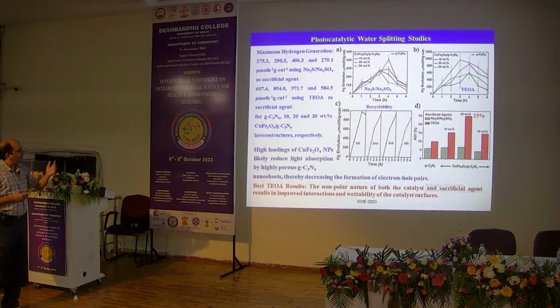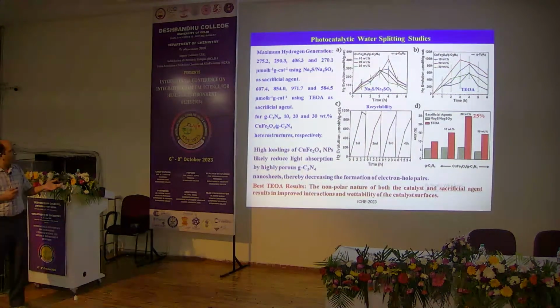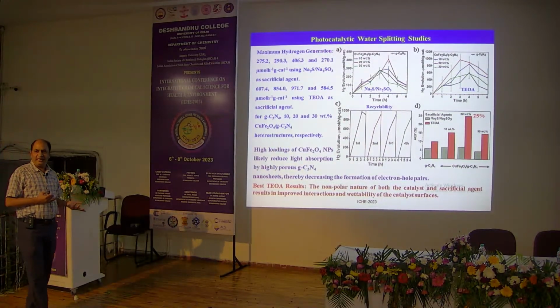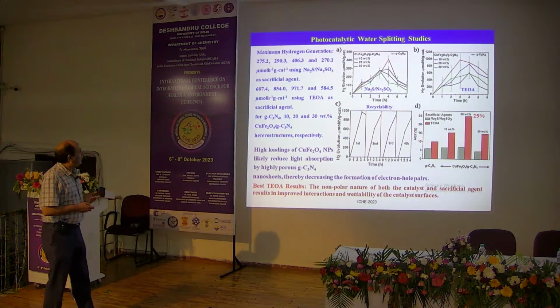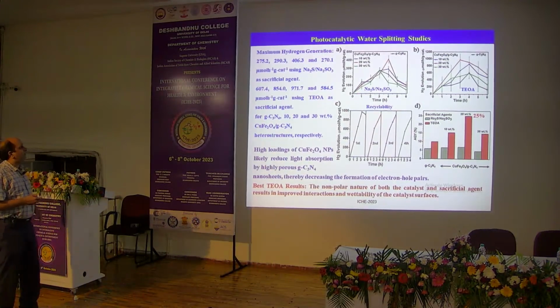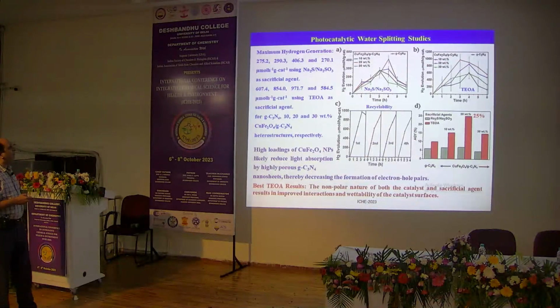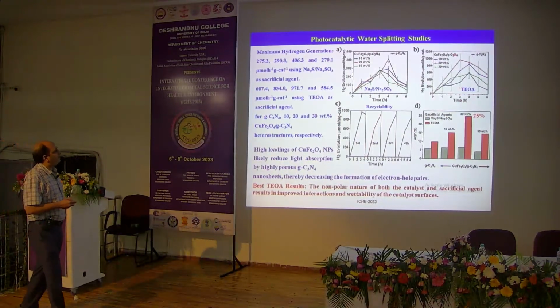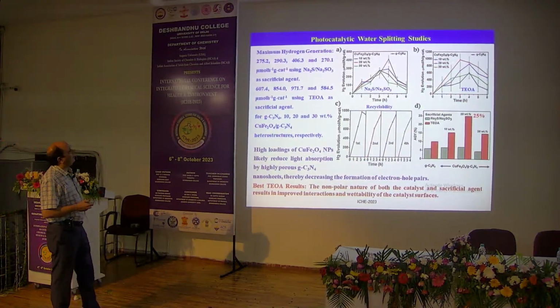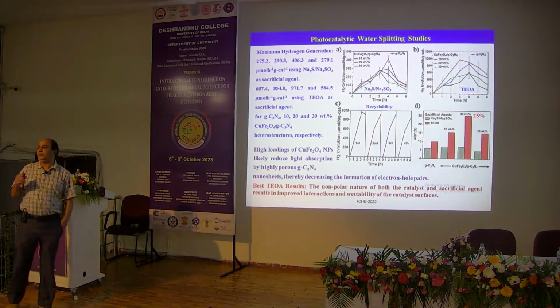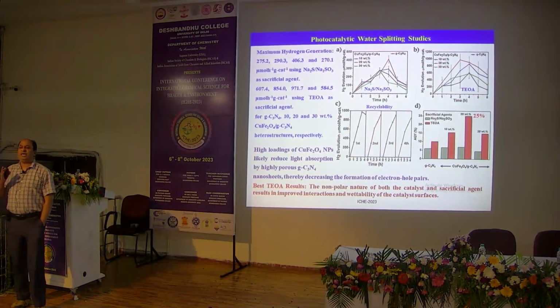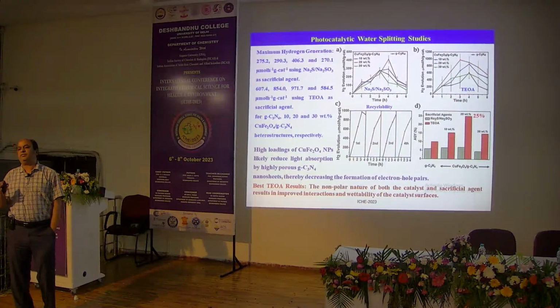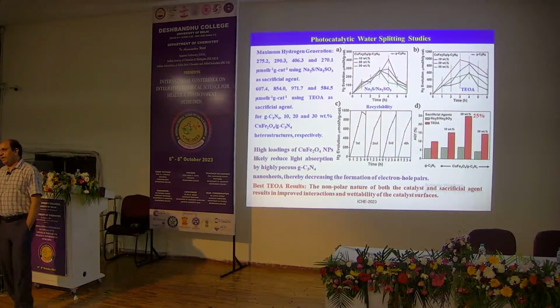And then these are the photochemical hydrogen generation. Again, we made two sets of reactions, one with sodium sulfide, which gives a lesser amount of hydrogen, whereas triethanolamine gives a high amount of hydrogen. Here we obtained the maximum amount of hydrogen production by using the 25% copper ferrite loading over the